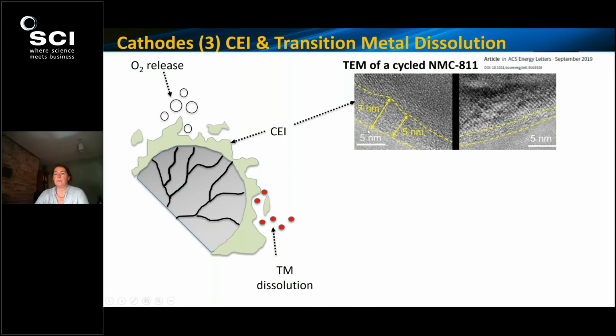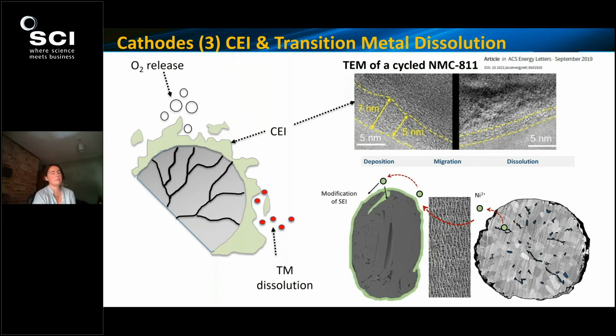And in the top right, you can see TEM images. So again, these films are of nanometer dimension thickness. And it just means that it's another domain whereby we can irreversibly trap lithium. But also, and interestingly, as the cathode chemistry evolution has journeyed into new chemistries, a lot of studies have looked at the dissolution of certain transition metals from the cathode that can inadvertently migrate towards the anode and actually modify the SEI on the anode, which can have an effect on performance.